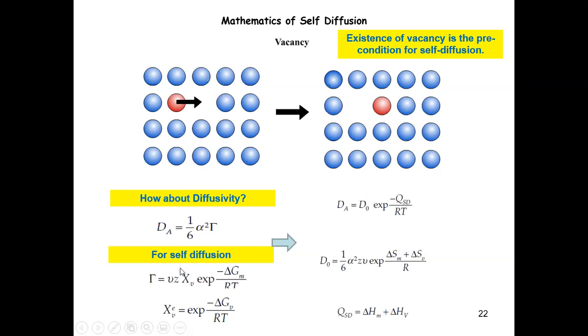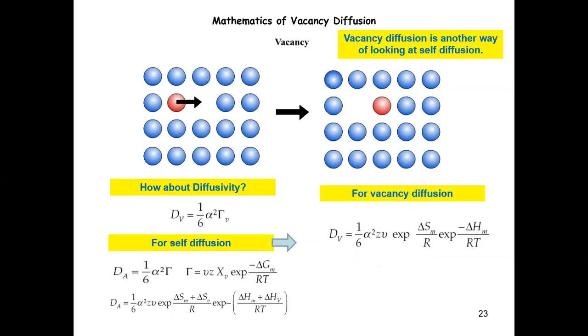Okay, but the key thing here is to realize that the key difference between substitutional diffusion and interstitial diffusion is that substitutional diffusion has to involve a vacancy, and that's going to significantly reduce the actual diffusivity for the system in general. Other than that, all the mathematics are the same. All of the tricks we use to measure diffusivity are the same. And most of the physical considerations are also the same, right? The only thing is that we have to take into account the vacancy. Okay, that's that.